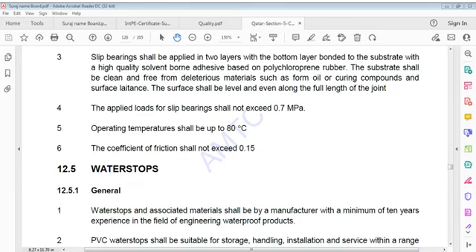Applied loads for slip bearings shall not exceed 0.7 MPa. Operating temperature shall be up to 80 degrees Celsius. Coefficient of friction shall not exceed 0.15.